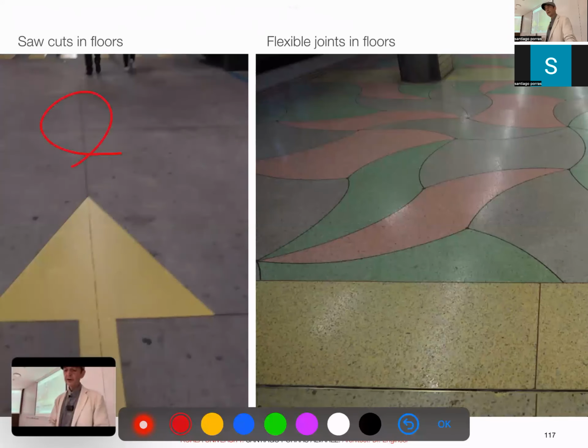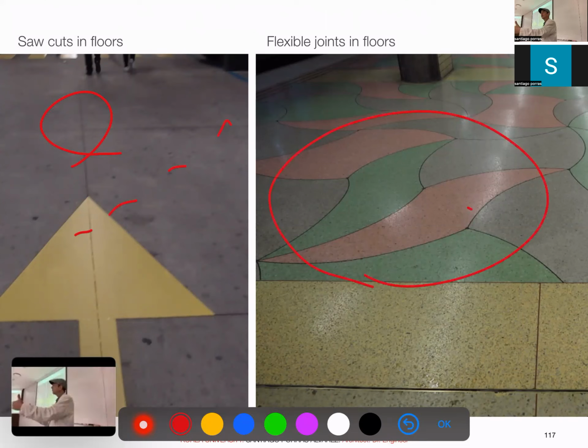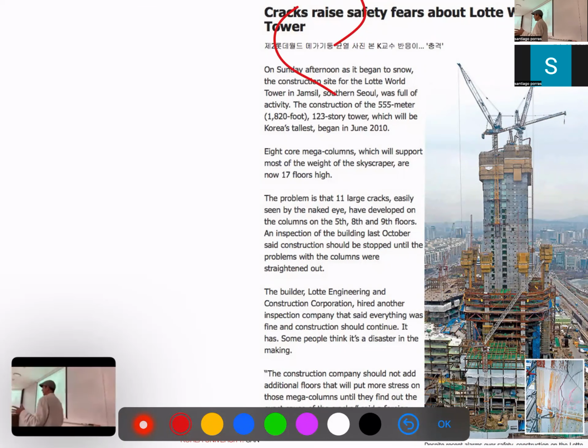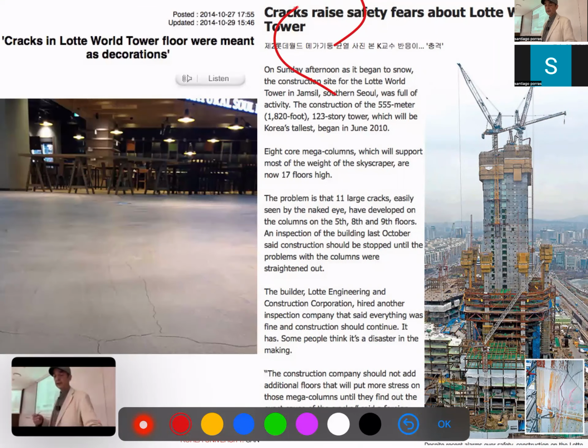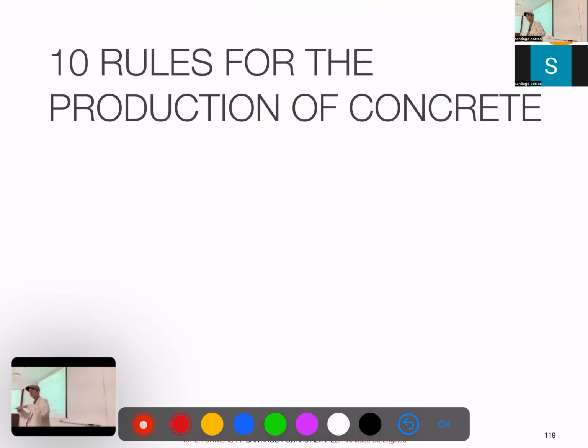In floors, for example, people will cut it once hardened, in squares like 3 by 3 or 4 by 4 meters. And still it can crack, right? Or you may put flexible joints, so you have very small bits of concrete. So the effect of retraction and expansion later will not be so visible. And the cracks are natural. We try to avoid them by being more careful with the reinforcements or with additional fibers, but it's always annoying, right? And those cracks appearing always in the news were probably just due to the nature of the concrete material, not really being pathological, not being a problem of the structure. Being able to distinguish between both is important, but it's a little bit beyond our course.